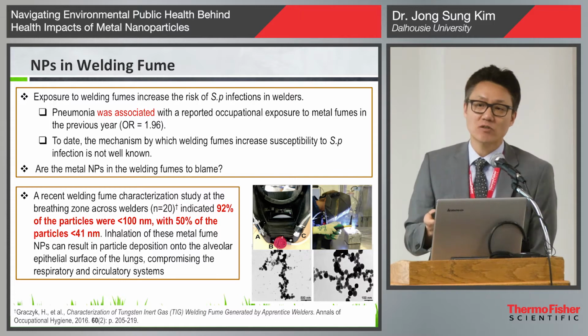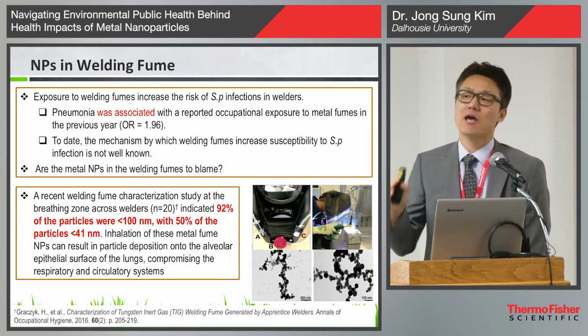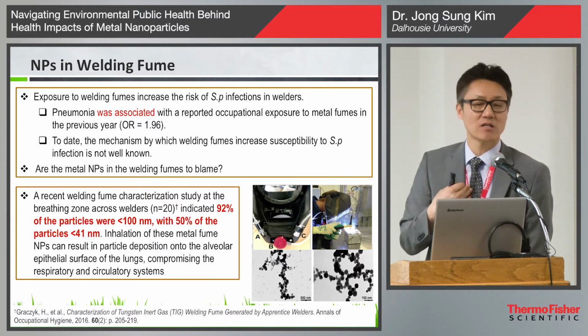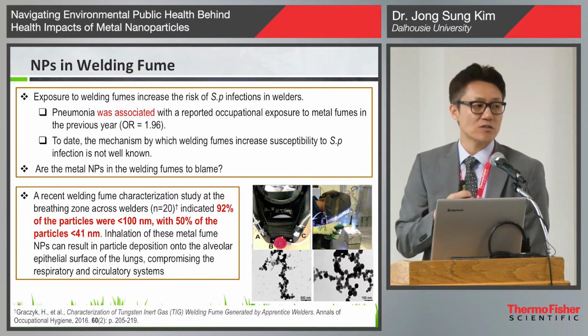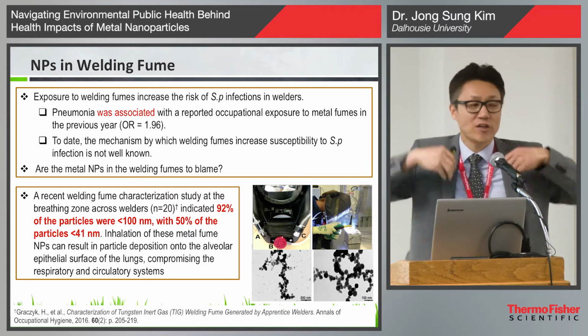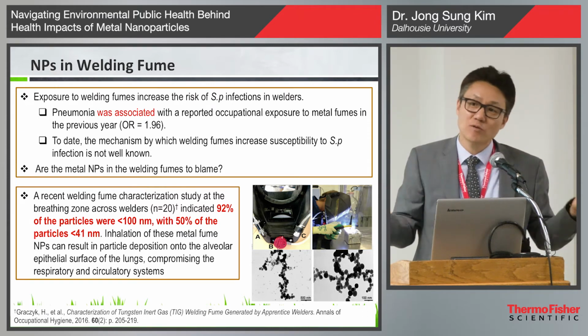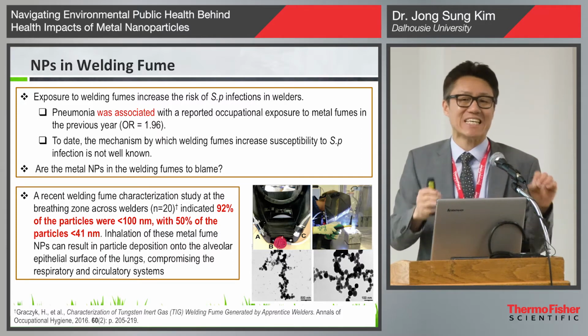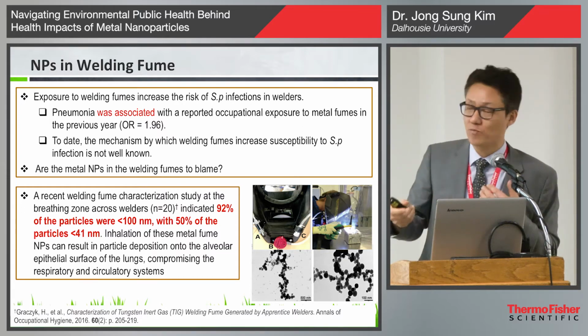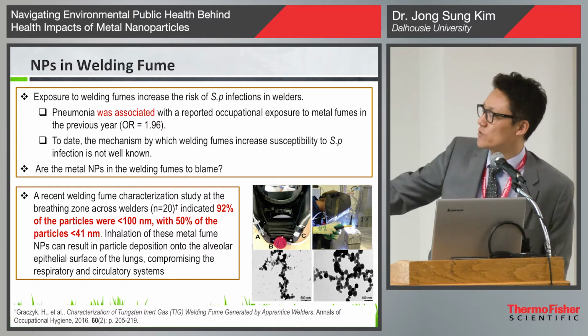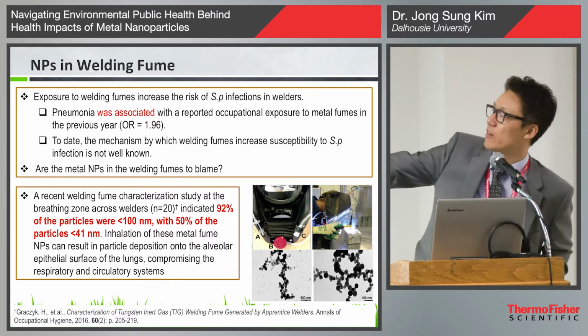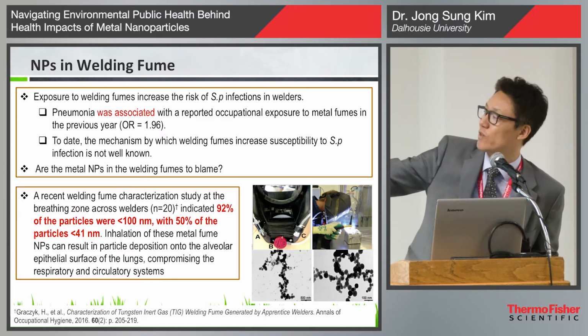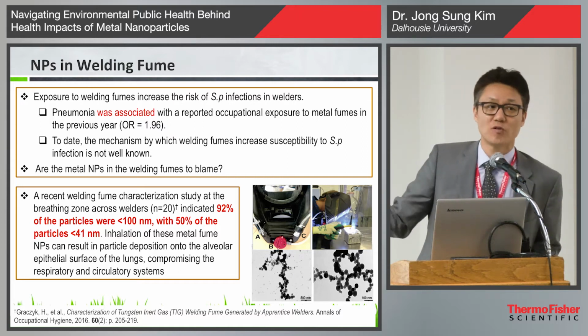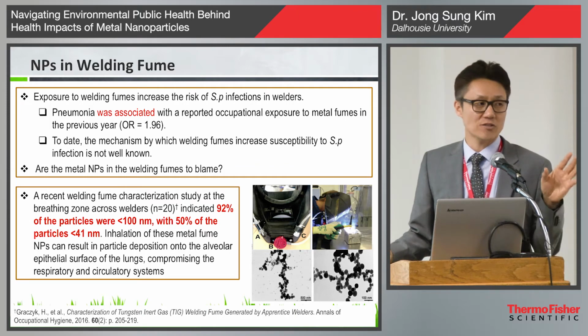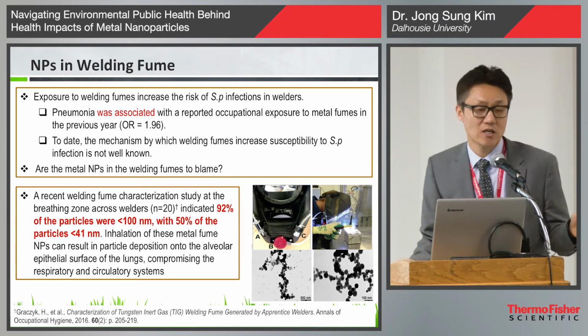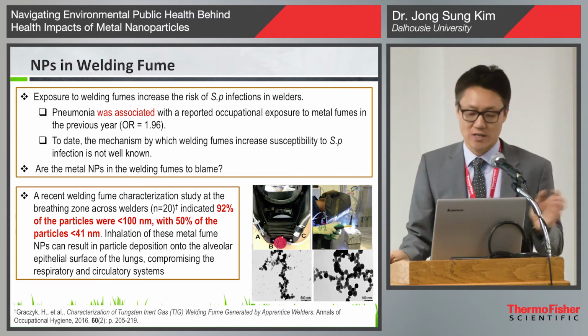So we thought maybe nanoparticles in welding fumes increase bacterial adhesion ability to lung cells, because before lung infections, bacteria first deposit on the lung cells, and then they are happy there, they grow and develop pneumonia. So we thought that, for whatever reason, metal nanoparticles in welding fumes increase bacterial adhesion ability in the cells, and then the bacteria grow. A recent welding fume study shows that welding fume is predominantly made of nano-scale particles: 92% of the particles are smaller than 100 nanometers, and 50% of the particles are actually less than 41 nanometers. Current regulation for welding fume health impact is based on mass, not size, even though the mass is just below the 2.5 micron size.